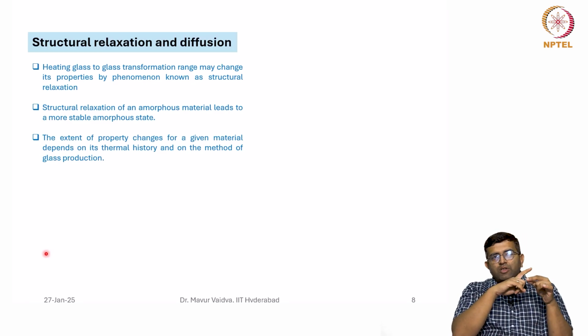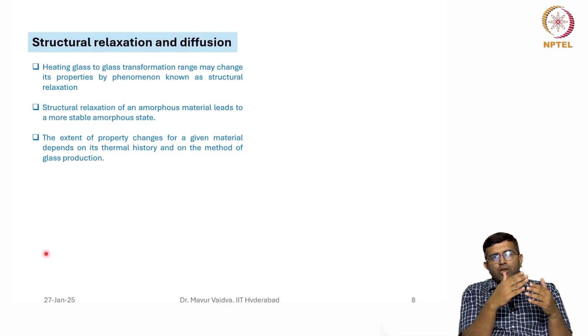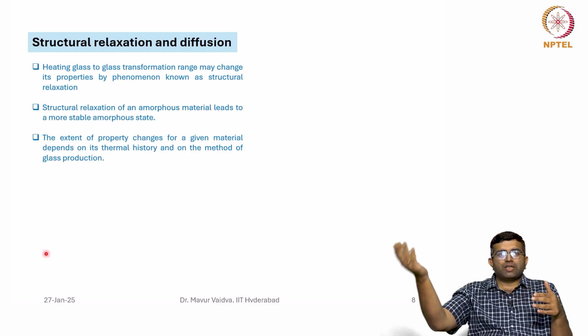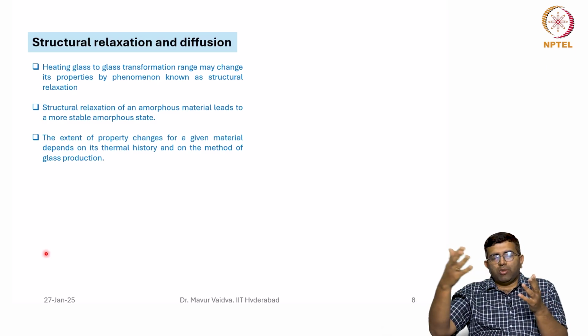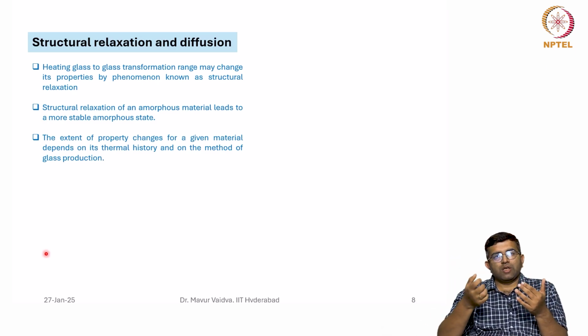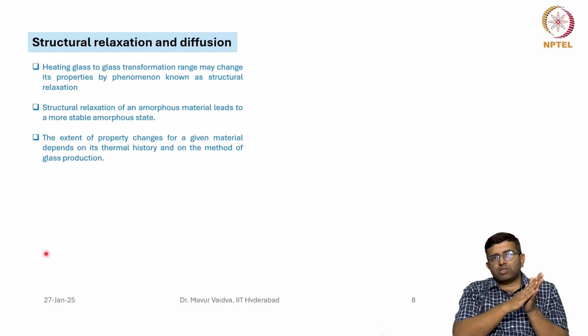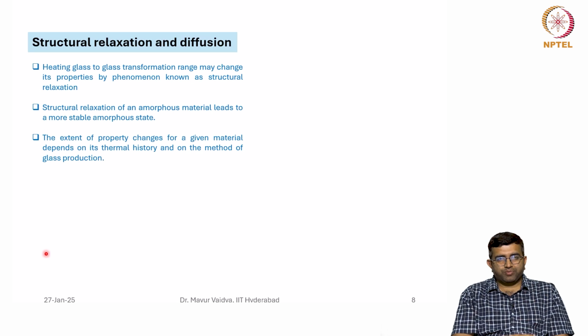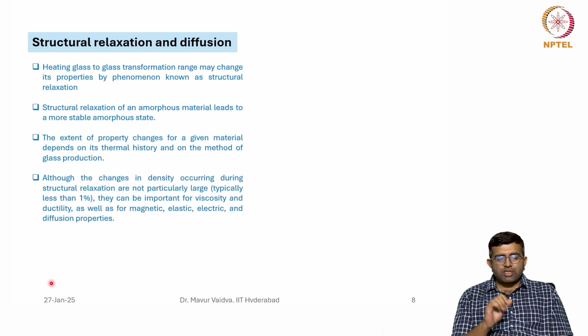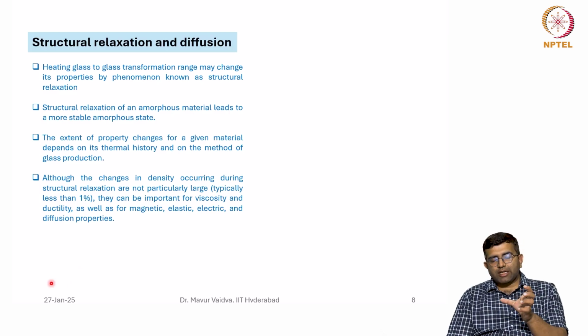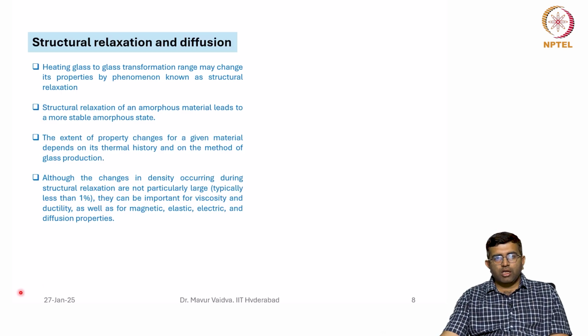Remember, when we talk about structural relaxation, we are not heating the glass beyond the crystallization temperature, because then obviously it becomes crystals and everything will change. What we are talking about is heating the glass to the glass transformation range, which means above the glass transition and below the crystallization temperature. Although the change in density during this structural relaxation is not huge, it can have an impact on properties like viscosity and ductility, as well as magnetic, electric, elastic and diffusion properties.